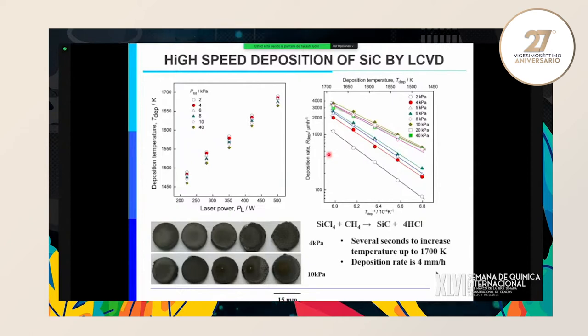So this is an example of silicon carbide by laser CVD. By using common precursors, silicon tetrachloride and methane, the deposition rate increased with increasing temperature and also with increasing total pressure. So it becomes around 4,000 micrometers per hour. So we can make bulky silicon carbide at very high speed by using laser CVD.